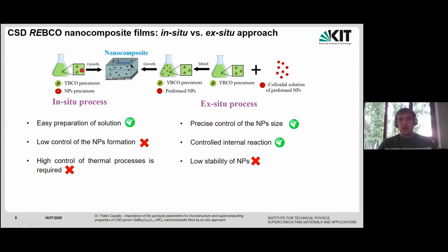And in this case, the nanoparticles are already there, so they are just embedded in the matrix during the growth. The advantage of this process is that we have, theoretically, of course, it's not so straightforward, but theoretically we have a precise control of the nanoparticle size, and we have a very precise control also of the internal reaction. So we have something that we cannot really control in the in situ approach, and this is the advantage of this process.